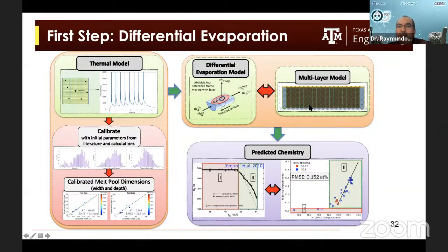So what we did was we printed coupons with different processing conditions, and then we measured the transformation temperature using DSC. It turns out that measuring chemistry is very uncertain. The uncertainty in WDS is plus minus 0.5%. And here we have a change of a fraction of that, and you can see how much the transformation temperature has changed. So instead of doing chemistry or doing analytics to find the chemistry, we actually measure the transformation temperatures, which we think is a more precise way of measuring indirectly the chemistry, at least in this region.